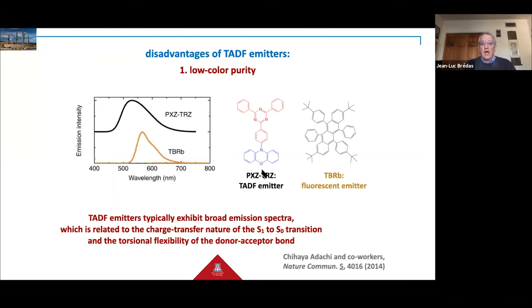For instance, because those molecules are designed with an electron donor component and an electron acceptor component, their transition from the lowest singlet state back to the singlet ground state has a charge transfer character, which leads to a broad emission and low color purity, with respect to what can happen in purely fluorescent emitters, such as this rubrene derivative that has a much sharper emission.